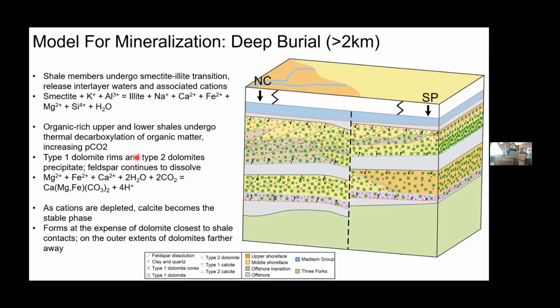At the same time this is happening, the organic rich upper and lower shales are undergoing the thermal decarboxylation of organic matter, which increases the partial pressure of CO2 within the Sappington. And that would have promoted carbonate precipitation. So during this time, type 1 dolomite rims and type 2 dolomite rims precipitate, and in a lot of cases, they're dissolving feldspar due to that increase in CO2. So we can derive those minerals directly from the ions that are released from the shales to precipitate ferroan dolomite shown here.